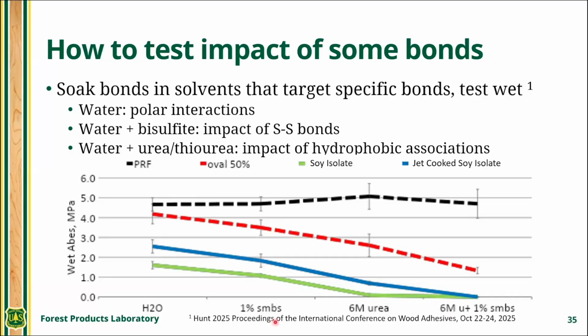Then we took samples and soaked them in water plus 6 molar urea. Urea and thiourea impact hydrophobic associations, make them weaker. And so you can see the impact on the strength. Urea reduces the strength because those hydrophobic interactions are contributing. And then you can mix the two. So here's just a way to probe the adhesives. And if anybody has ideas for other solvents you can use to probe other reactions, or other covalent bonds, I'd love to hear from you.